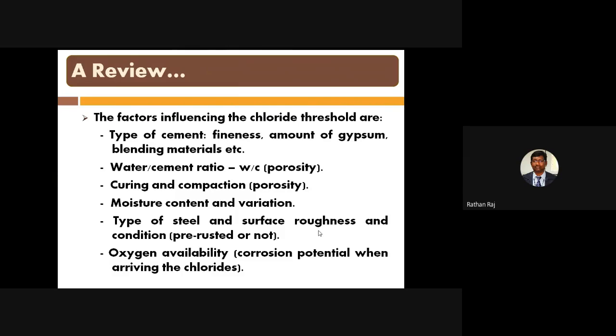The second one is the water cement ratio. We use different water cement ratios to improve the strength of the concrete by lowering the water cement ratio. If you lower the water cement ratio, we have to take care about any porosity in the concrete, that means any voids in the concrete. So we have to take necessary care in the compaction also.